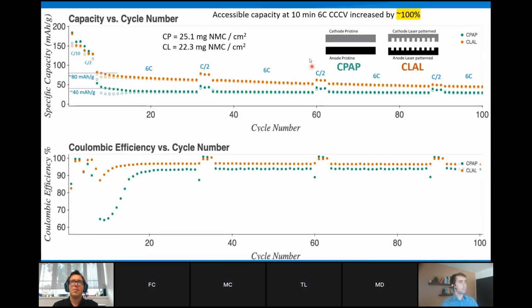And here are some of the results. So here on the y-axis, specific capacity, milliamp hours per gram of the NMC. On the x-axis, the cycle number. Green is the cathode pristine, anode pristine, or CPAP. Orange is the cathode lasered, anode lasered. So this is the benchmark in the pristine, and then the lasered channel in orange. And we can see at 6C for this thick electrode.